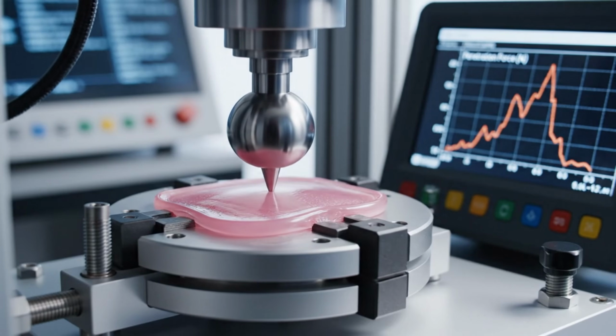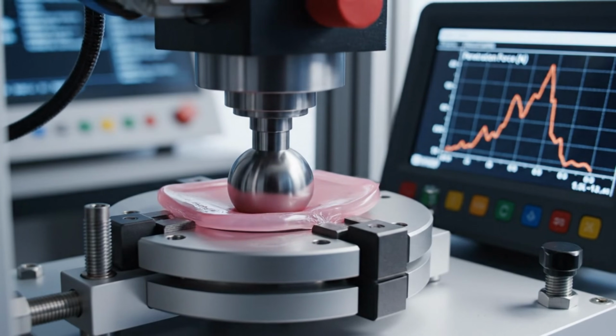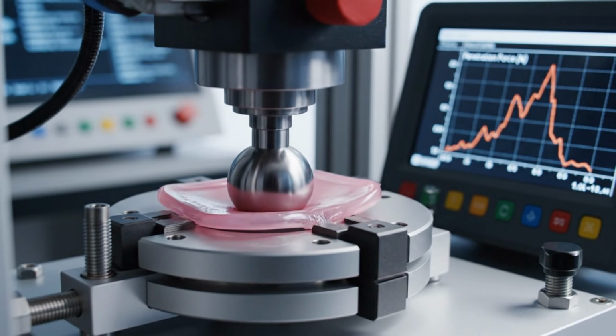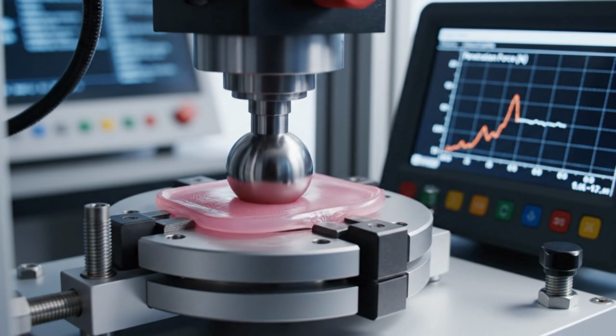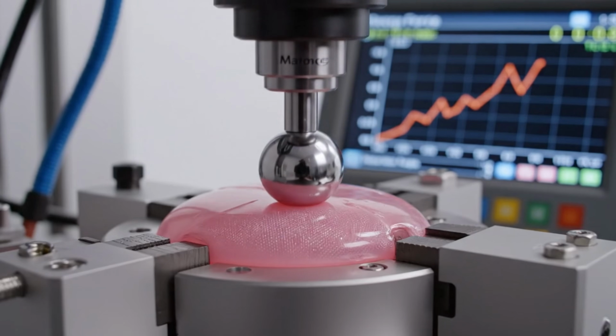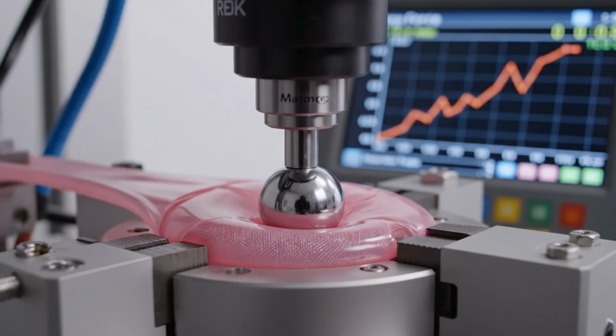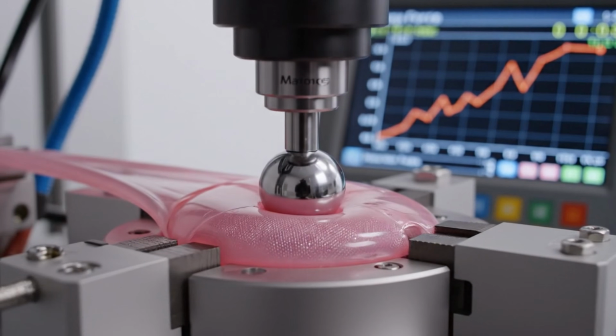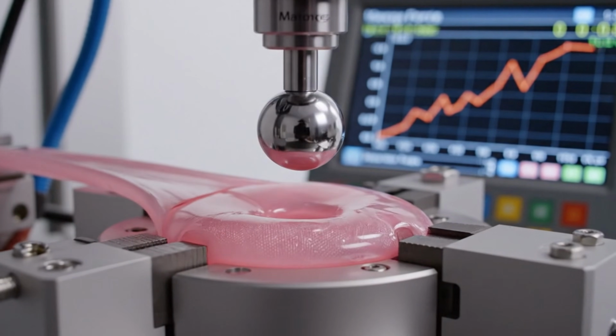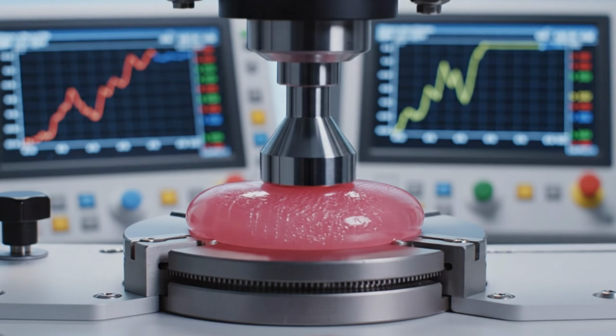A spherical probe presses a pink female condom sample while the monitor records the force curve in real time. The material must withstand at least 9 pounds force of point pressure before perforation, simulating extreme mechanical stress conditions during use.